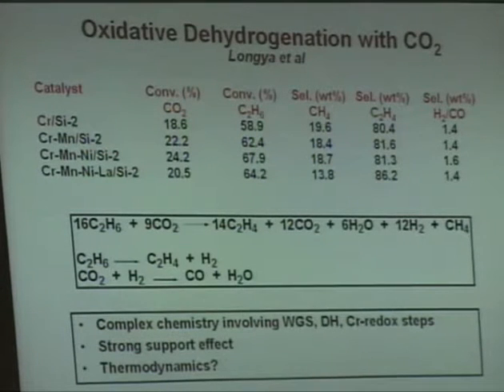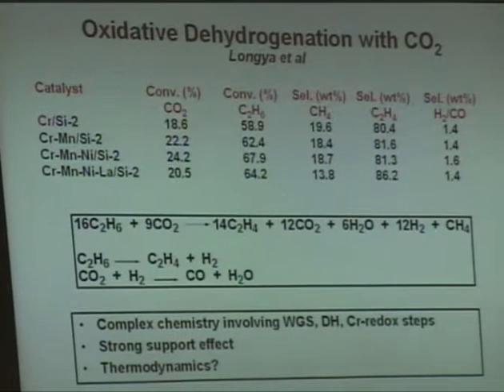But you think about the thermodynamics, and it's a very complicated reaction which they have published. And they claim it takes place in two stages. There's this conventional dehydrogenation of ethane to ethylene, and then there's the reverse water gas shift reaction here, the hydrogen reacting with the CO2 that's present to generate CO and water. So that's how the hydrogen is removed from the reaction to shift the equilibrium.